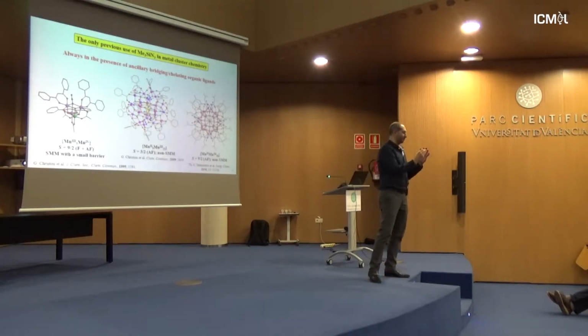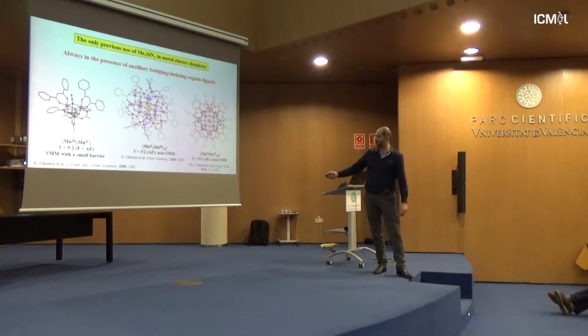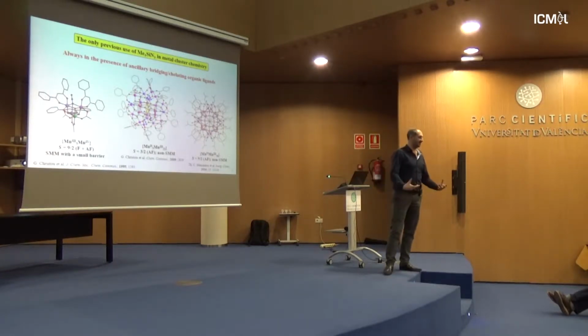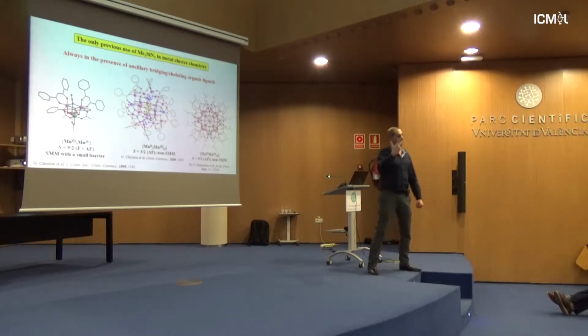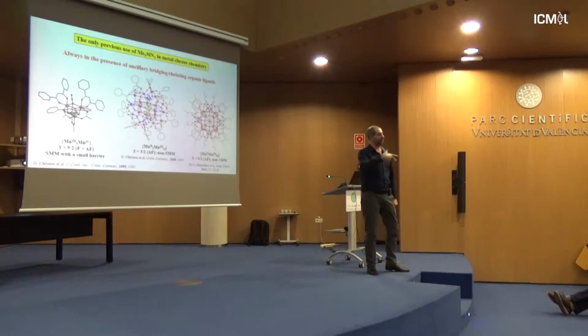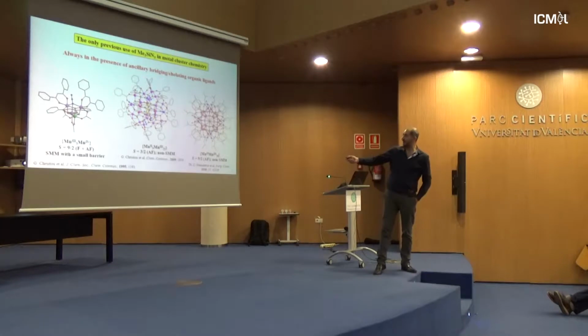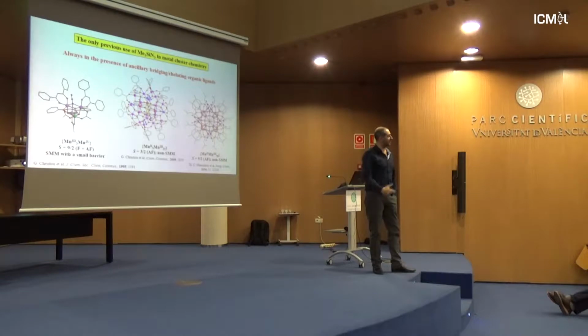What does that mean? We used trimethylsilyl azide to make manganese carboxylate clusters, which will also have end-on azides. Fantastic chemistry, we got new cluster compounds, look at them. All of them super small spin states. Essentially, all of them antiferromagnetically coupled. Why is that? Again, for the same reason that we see all of these myriads of compounds in the literature, and they're antiferromagnetically coupled. Carboxylates, oxides, of course some azides. The overall behavior is predominantly antiferromagnetic. No guarantee.